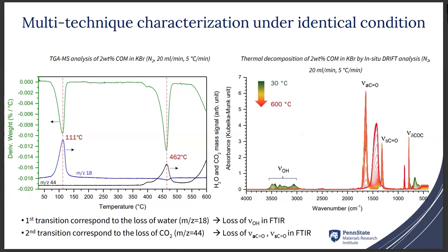And that's why I did this comparison with the TGA under the same condition for the FTIR, because I had to reduce the ramp to 5 degrees per minute in order to make sure that I have identical data.